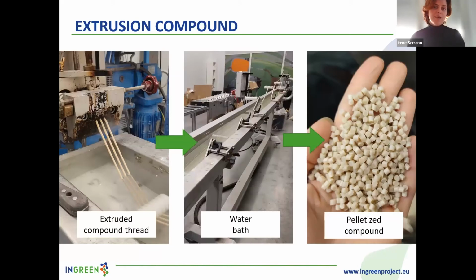After being mixed, the resulting compound gets out of the extruder through a circular cross-section die in the shape of a continuous thread, and it passes through a water bath in order to be cooled down. At the end of the water bath, the thread is introduced into a pelletizer station and gets cut into small plastic pellets, ready to be converted afterwards into films.